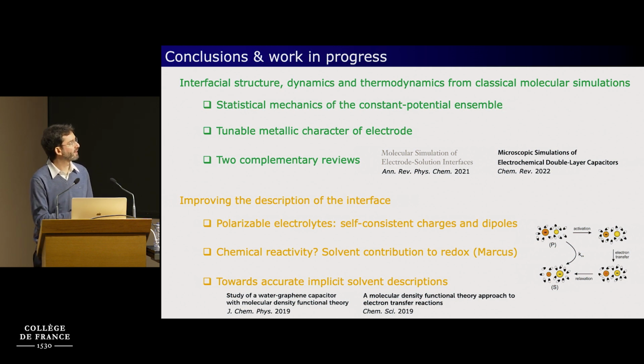I would say just a few words about work in progress in order to improve the description of the interface. It's in fact already possible to also consider a polarizable electrolyte. You just need to consider self-consistently the induced charges in the metal and the induced dipoles in the electrolyte. You can capture some aspects of chemical reactivity already with these simple models, focusing on the solvent contribution to redox processes, as in Marcus theory. And we are making an effort, especially my colleague Guillaume Jeanmairet, to have an improved implicit solvent description compared to simply having a continuous medium with a permittivity, especially based on molecular density functional theory.